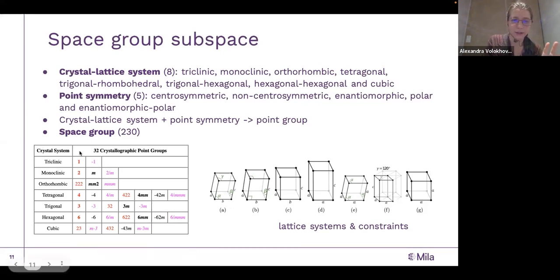But the crystal system is not enough for us because we're also interested in the constraints for the lattice parameters. So we combine it with another categorization, which is the lattice system. Lattice systems are similar in terms of names and separation to the crystal systems, but they do not coincide perfectly. That's why we have these eight combined crystal lattice systems: triclinic, monoclinic, orthorhombic, tetragonal, trigonal-rhombohedral, trigonal-hexagonal, hexagonal-hexagonal, and cubic. Given this number, we can first separate point groups into non-intersecting groups, and we also have the constraints for the lattice parameters.